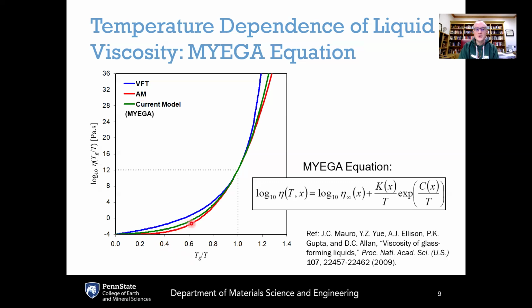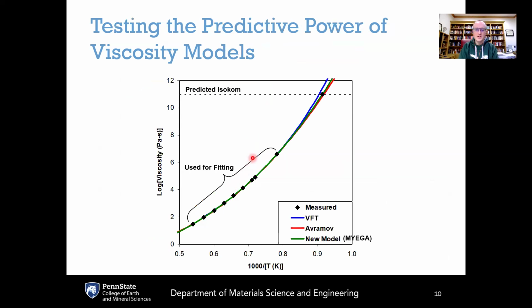That is being shown here in red, and that has the least amount of curvature of the three models. In order to test these three models in terms of their ability to predict the low temperature viscosity, we put them to a test of several hundred different glass compositions, used each of the models to fit the high temperature viscosity data, and then extrapolate the models to predict how the low temperature viscosity would scale. Then we would compare those predictions to actual measurements of the low temperature viscosity, in this case at 10 to